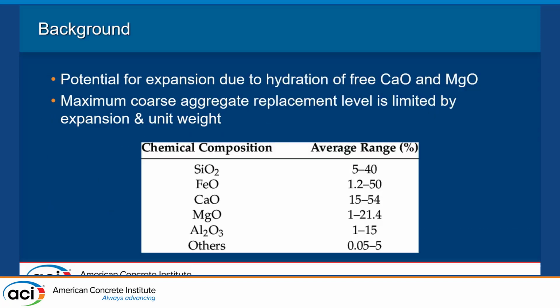So the main concern regarding the application of EAF slag as a coarse aggregate is its potential for expansion due to the hydration of the free calcium oxide and free magnesium oxide that make up a large percentage of the EAF slag's composition. While hydration is, of course, a fundamental reaction in cement chemistry, if too much expansion of the aggregates results, it could lead to tensile stresses on the concrete, leading to undesirable cracking, which, of course, can affect the structural integrity of our concrete mixes. Therefore, we found that the replacement levels end up being limited mainly by this expansion.